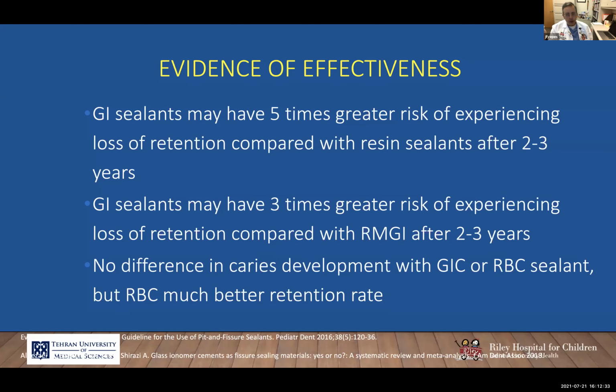I'm sure in Iran, you are using, in some circumstances when isolation is very challenging, glass ionomers. We are using glass ionomers here as well, but the evidence shows that when you use glass ionomer as a sealant, the retention of the GI is not as good as the retention of the regular sealant. So if you decide to use GI because you have an isolation issue, like you have a patient with high caries risk and you want to place sealants in partially erupted permanent molars, when doing a good isolation is almost impossible, and then you decide to use a GI, which, as you know, is less sensitive to moisture, you need to be careful because in terms of retention, that probably will not be as good as using the traditional sealant.